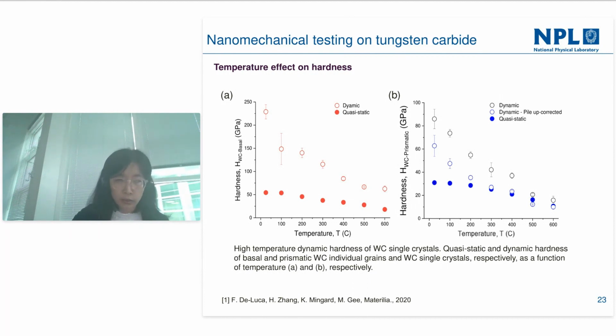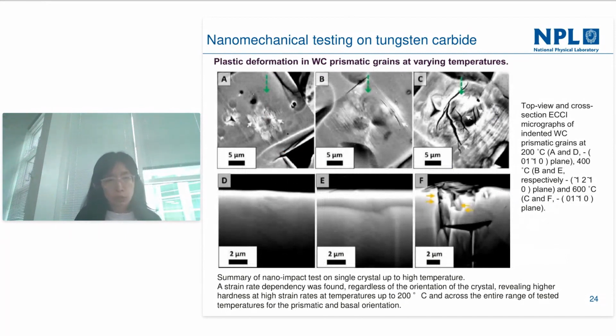We also checked the cross section of the two grains after the impact test, and from both quasi-static and impact test modes. We checked both the surface and cross section ECCI images, and we could see they show similar dislocation patterns and slip planes, which shows the deformation at high temperature is carried out at higher strain rate as well.